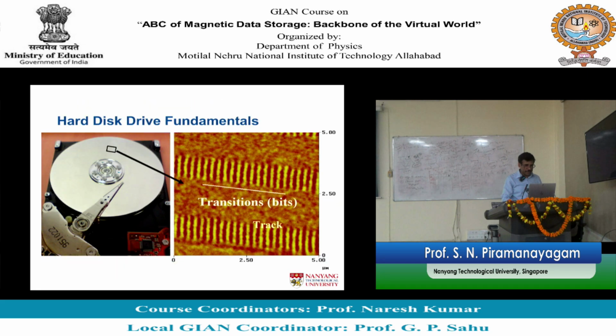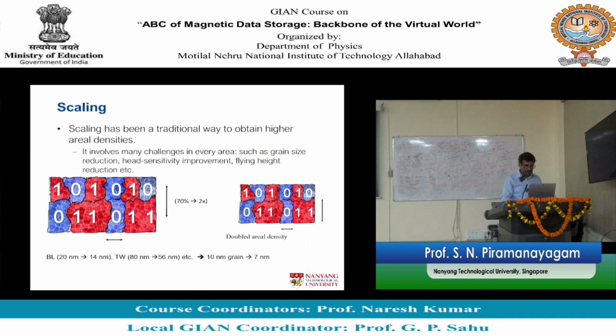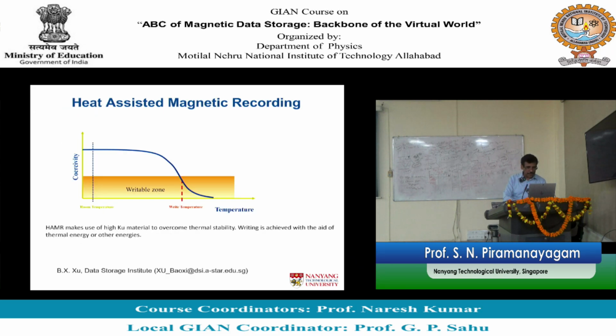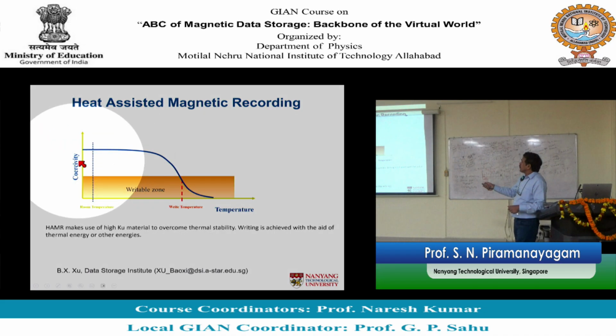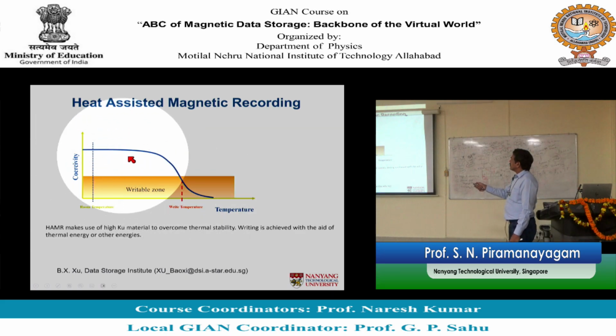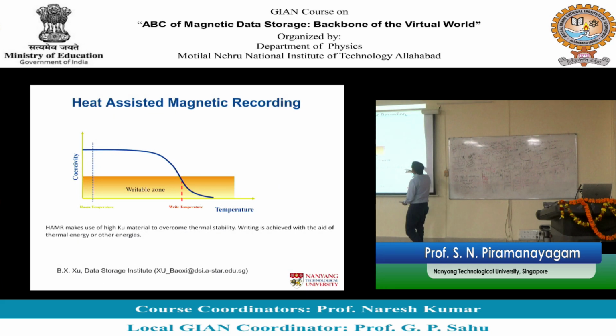So, we all learned this already. We do scaling to go towards high density, thermal stability we learned. Okay, so when it comes to heat assisted magnetic recording, we follow this property. If you plot the coercivity as a function of temperature, it will reduce at certain elevated temperature. Let us say your head can produce a magnetic field as high as this one. Then if you operate in this range, the available field is more than the coercivity of the material. So, you can write information. Okay. So, that is the concept behind heat assisted magnetic recording.